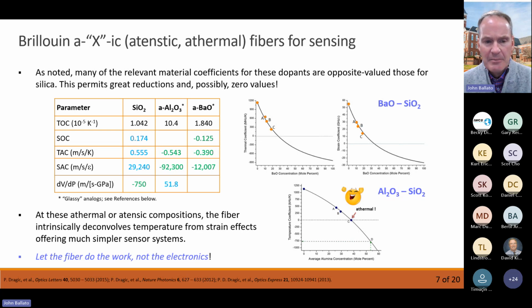It's athermal. That means its temperature behavior is 0. That makes it only strain sensitive. So normally in sensors, you have temperature and strain, and you have contributions from both of those things. So if you have a sensor and you say, well, I don't know if the change is because of temperature or because of strain, the way that is deconvolved is through the electronics, or you have to have a sensor system that has multiple fibers, each with a different temperature and strain dependence. And then you have all the complicated electronics and circuits to then deduce, okay, well, what is the strain? What is the temperature? We have a fiber here that is only strain dependent. The temperature dependence goes away because it's athermal in its Brillouin response.